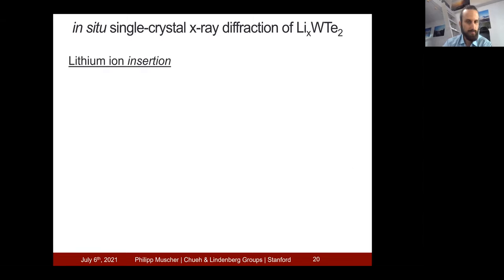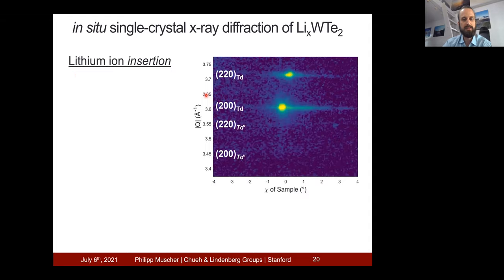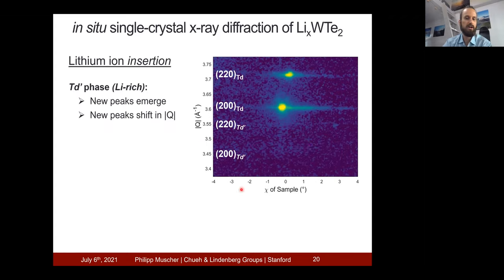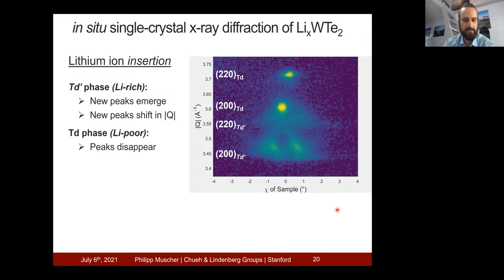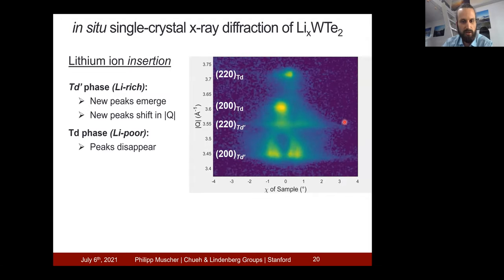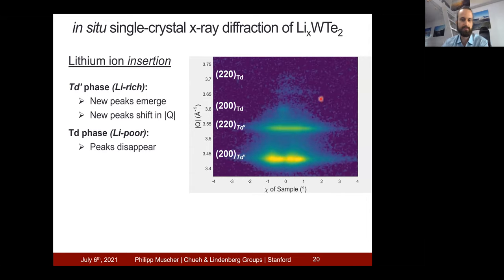So we can look at how this diffraction pattern evolves while lithium is being inserted into the material. This is a video, and I want to direct your attention to these two peaks, which will be disappearing. They correspond to the initial phase. And then new peaks will be appearing that correspond to the new phase. So let's look at this structural evolution. You can see new peaks appearing over here and the initial peaks disappearing.